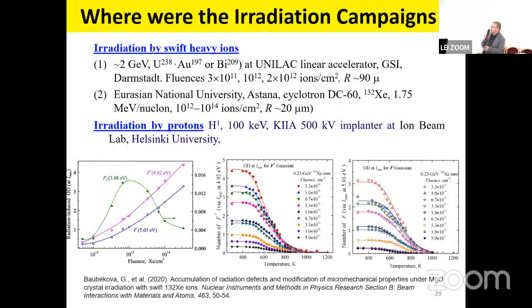We performed several measurements in different places: in Darmstadt, in Astana, in Helsinki. Two years ago, I also mentioned that we used Dubna in Russia, but now this is politically not good to mention. But we use many places for irradiation. And this is just an experimental example. You can see, for example, fluence and optical density in MgO. You can see how many points we obtained from a single irradiation campaign. Please believe me, you will never find data like this obtained after neutron irradiation. Such data simply do not exist.